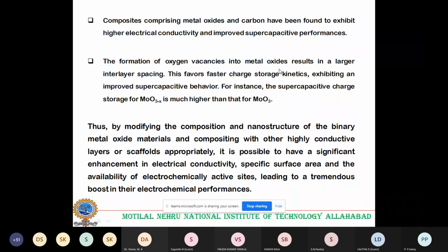This favors faster charge storage kinetics, exhibiting an improved supercapacitive behavior. For instance, the supercapacitive charge storage of MoO3-x is much higher than that of MoO3. That is, if there are oxygen vacancies, that will enlarge your interlayer spacing, and that favors the supercapacitive behavior.